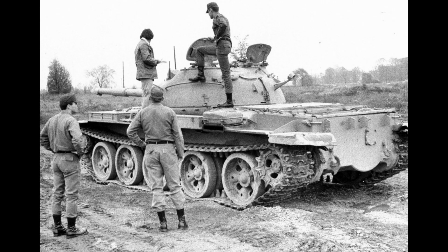He measured the crater depth, noting that the deformation extended deeper into the armor than he expected, but without the characteristic cracking that typically accompanied penetrations. The weld seams near the impact, which on earlier examined Shermans had shown a tendency to crack and separate under shock, remained intact. Something about this armor was fundamentally different from what German technical intelligence had documented previously. The sample Bäumer cut from the damaged Sherman required portable oxyacetylene cutting equipment and considerable effort.